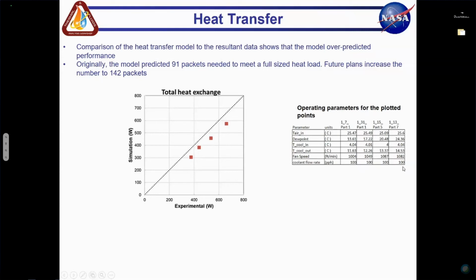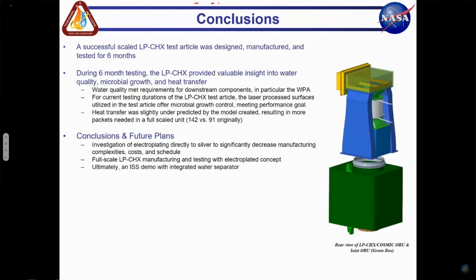In terms of our heat transfer, we have tons of data points from this, but this chart summarizes it nicely. Our experimental heat load that we got from testing is here, and we'd ideally expect that to line up with our simulation. We were slightly underperforming it with these red dots here. The test points that we took are from this right-hand side table. So we plotted those test points on it. They're slightly underperforming where we'd expect. And so the original model that we had predicted we need 91 packets to meet the full-sized heat load. And our future plans to increase the heat transfer is to increase that to about 142 packets.